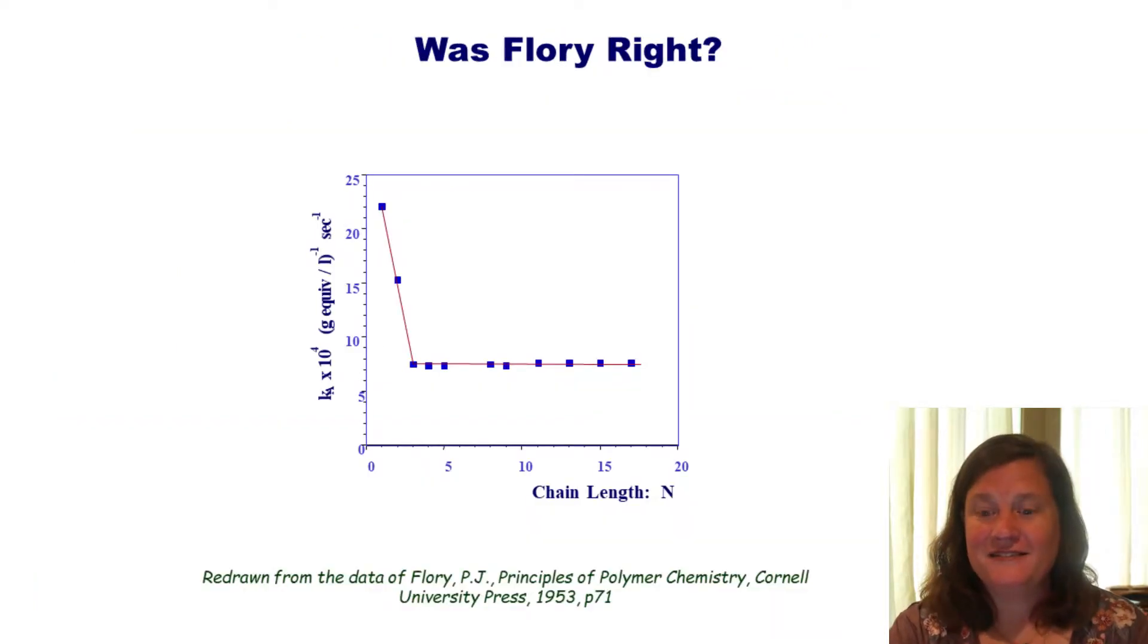So let's look at this plot. Is Flory right? Take a few seconds and look at it. This is real data from the 1950s that Flory published and it's really quite amazing how little variation there is from trimers on. The rate constant of an esterification just doesn't change once you get past monomers and dimers. So reactivity is independent of chain length except for monomers and dimers.